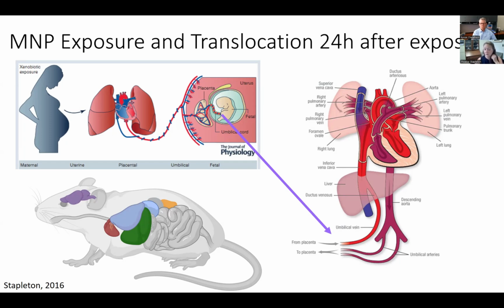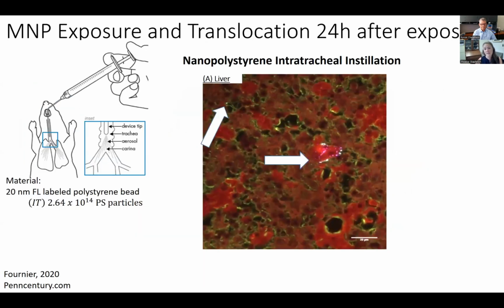So the rat here on the bottom left highlights the tissues that we looked at, starting with the liver and then the other systemic tissues, again from that fetal time point. So we did these exposures. We put the particles in the lung through intratracheal instillation. We left the animal for 24 hours after exposure. We came back, we did our dissections, we took our liver, and we stained them with H&E stains so that a pathologist could see if there were any gross morphometric or histopathology changes.